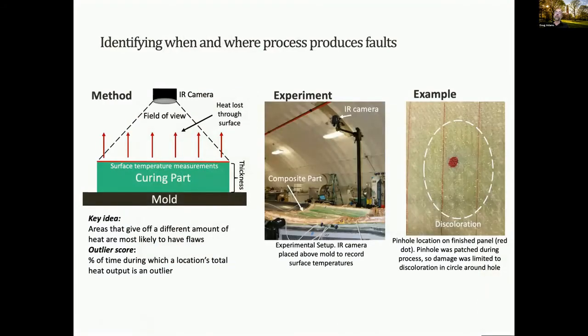And so the key idea in what we're doing is we're using, as I show here in this image, an IR camera to look at the surface of the mold in order to understand what temperature changes we might be seeing in the process, and how those temperature changes on the surface might be able to be used to infer that there might be flaws deep inside the part. And so what we're using is essentially an outlier technique. So we're looking for places where the heat is either too low or too high, indicative of something happening in the process.